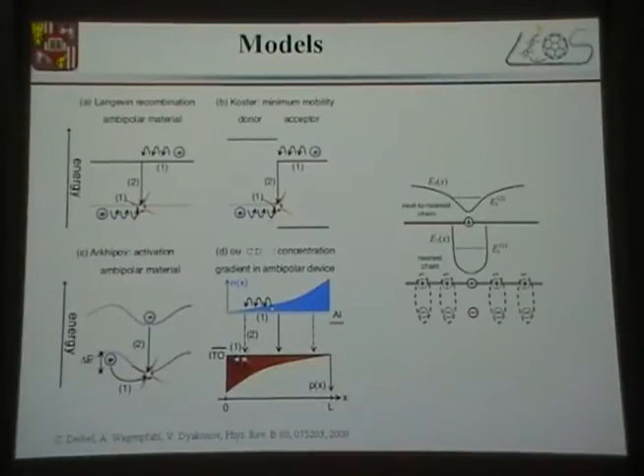There's been a model proposed that the recombination looks non-Langevin because in the P3HT:PCBM solar cells we have different phases, donor and acceptor, so the charge carriers cannot easily mix between each other. But in this case, if that would be the case, still the recombination coefficient will be determined by the slower carrier mobility. And usually in these P3HT:PCBM blends, the difference is 10 to 100 times between the mobility ratio, right? But we see that the bimolecular recombination coefficient, which we actually measure, can be up to 1,000 or maybe 10,000 times reduced. So this model cannot quite fully explain it.